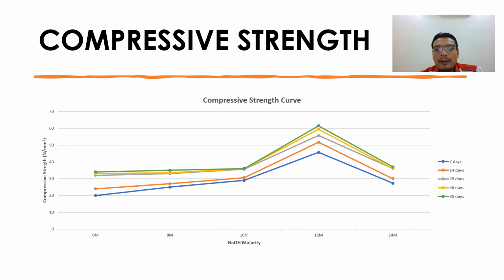The increment of compressive strength may be due to alkaline solution as an activator to fly ash in concrete via the geopolymer process. The compressive strength of the specimen was seen to decrease to 37 Newton per millimeter square when 14 molarities of sodium hydroxide at 90 days.